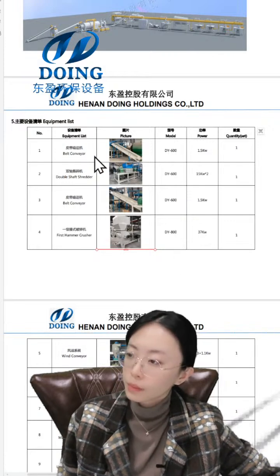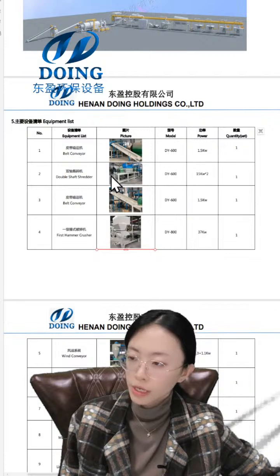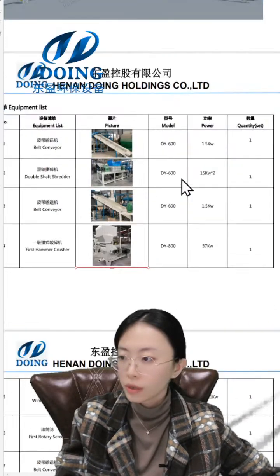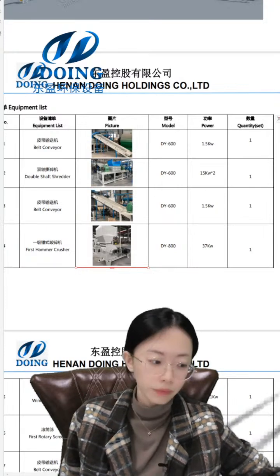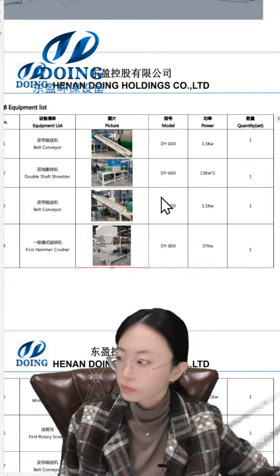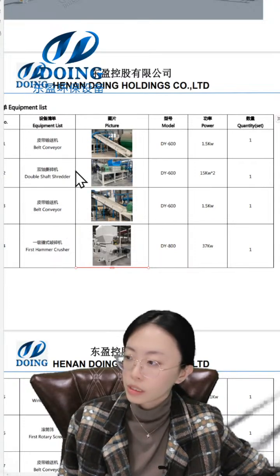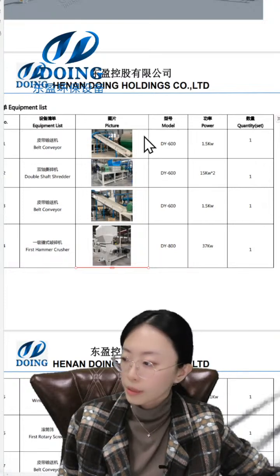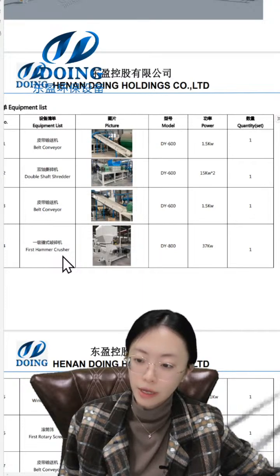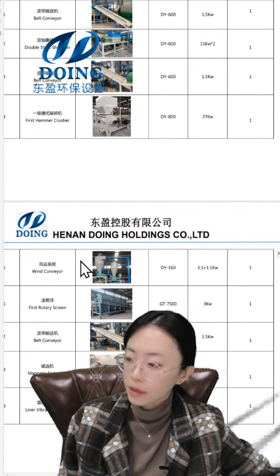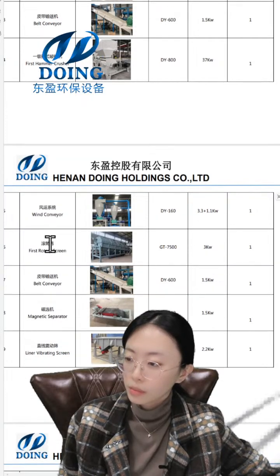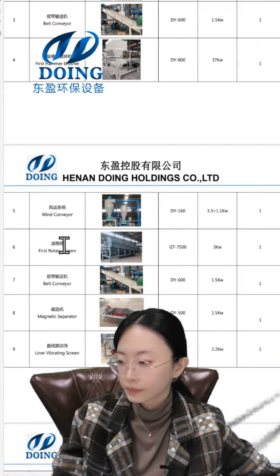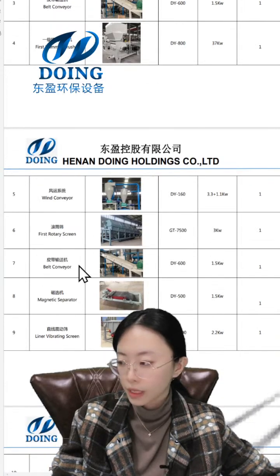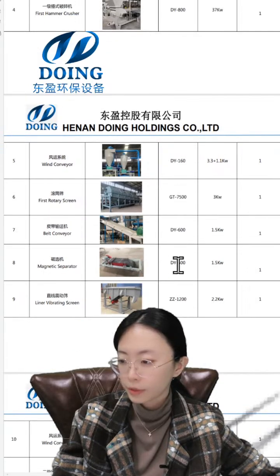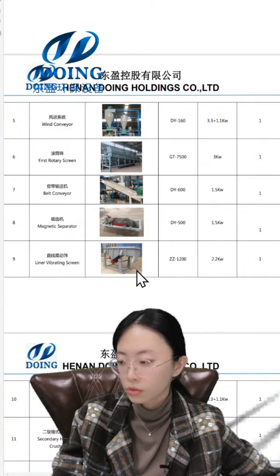You can see the first, a belt conveyor, and then the double shaft shredder. This has a power of 15 kilowatts. We have 2 double shaft shredders, and then the belt conveyor will link with the double shaft shredder and the hammerhead crusher. This is a hammer blade crusher. It has blades inside. And then the wind conveyor transports the material to the first rotary screen with 3 kilowatts, and the belt conveyor, magnetic separator. This is a linear vibrating screen to separate the plastic diaphragm.